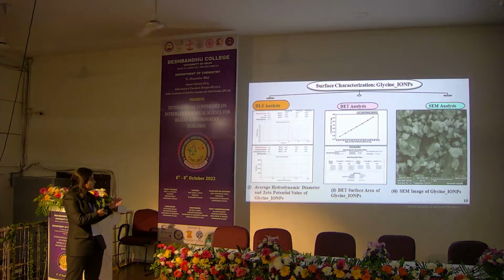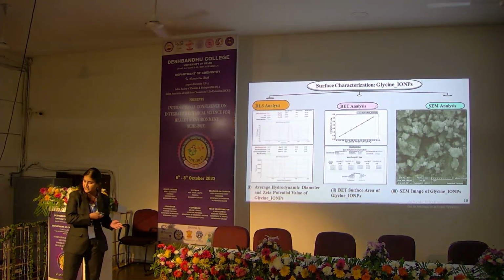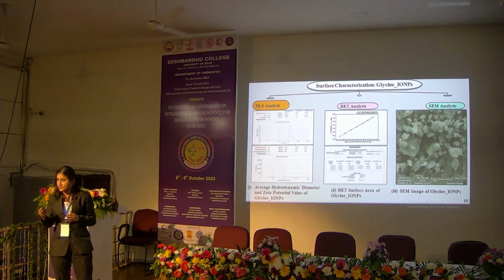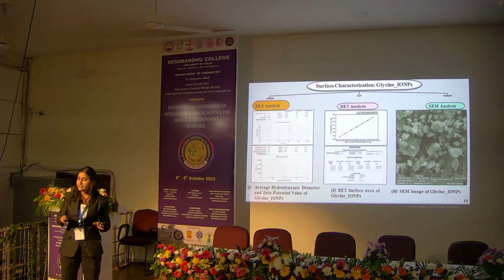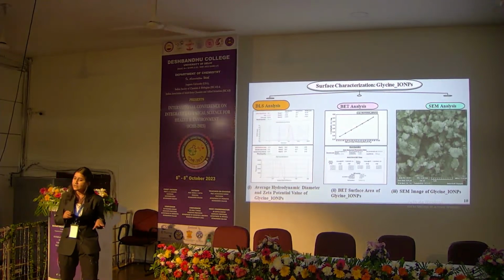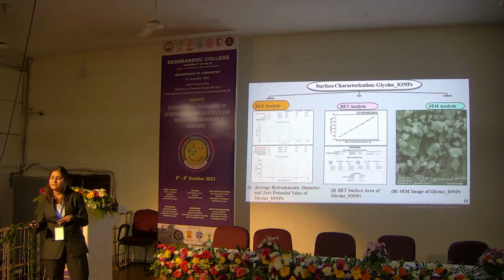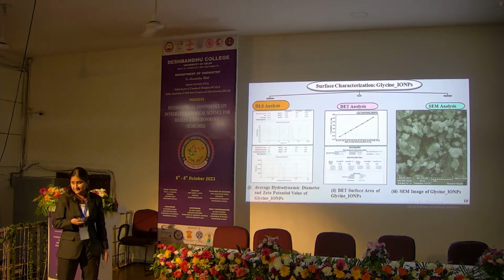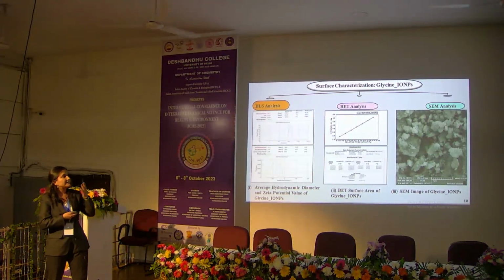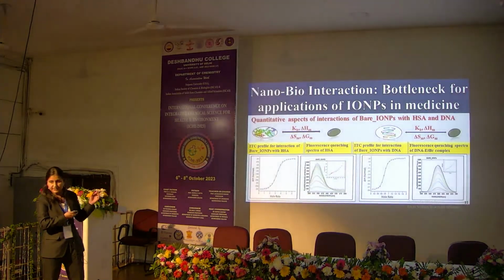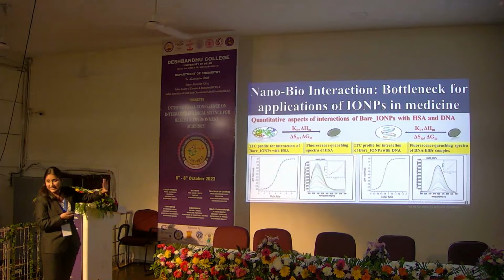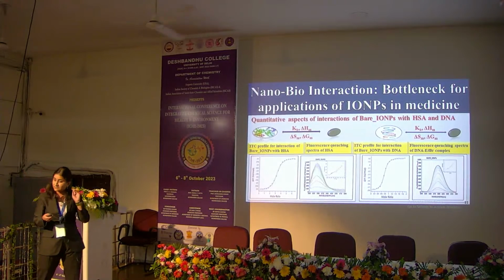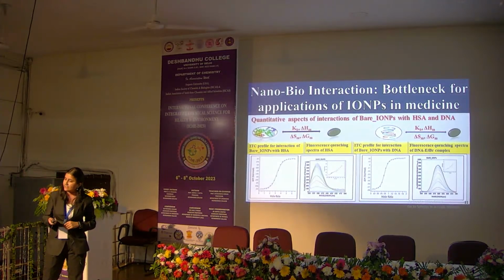Next, for the determination of the colloidal stability, we have performed zeta potential measurement studies, and the results suggest that amino acid coated nanoformulation showed a zeta potential value around 30 millivolt, and that for bare iron oxide nanoparticles it was around 18. This suggests that the amino acid coated formulations are colloidally more stable, and this was further confirmed by SEM analysis, as more clear images were obtained and they were well dispersed and colloidally dispersed.